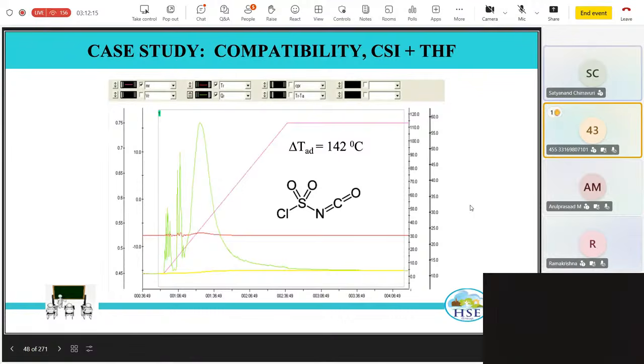In one incident, what happened was that chlorosulfonyl isocyanate was added at minus 20 degrees centigrade, and then tetrahydrofuran was added to the chlorosulfonyl isocyanate, kept at minus 20 degrees centigrade. But reactant B was not immediately available. So what they said was, okay, let us keep the solution on hold.